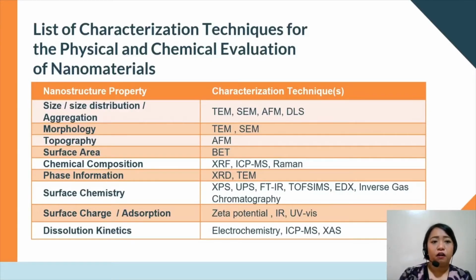Listed here are characterization techniques for the physical and chemical evaluation of nanomaterials. So we have here the nanostructure property on the left, and then on the right are the characterization techniques that can be used. For size distribution and aggregation, you can identify them using TEM or transmission electron microscope, scanning electron microscope, atomic force microscope, and dynamic light scattering machine. For the morphology, we can use TEM and SEM. For topography, we can use AFM as well. For surface area measurement, we can use the Brunauer-Emmett-Teller machine or BET.